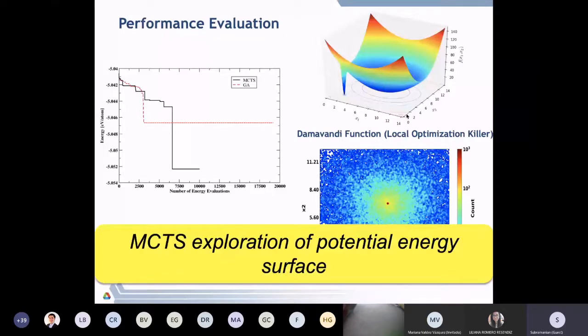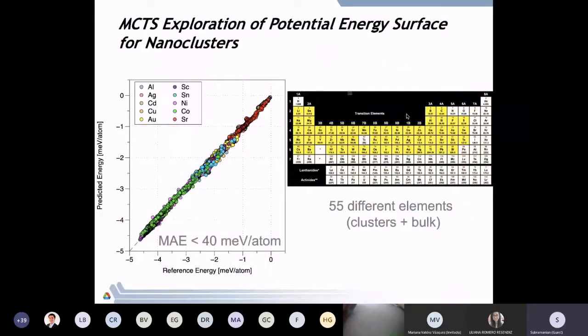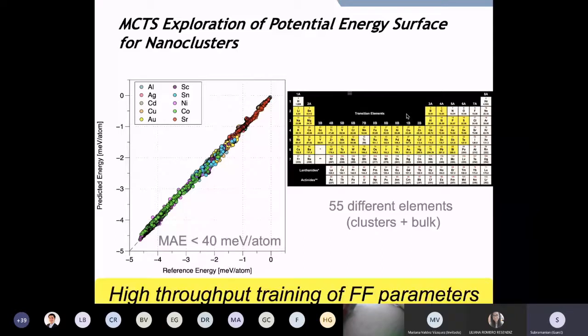So what we now did is that we went ahead and developed a force field for 55 different systems that had explicitly included training data for nanoclusters from DFT. And we came up with a model for 55 elemental systems. The process only takes a few hours to optimize the potential, and can be done on a single core, meaning that you can use your laptop to train force field parameters. So this is highly efficient and basically brings about this new era where we can do high throughput training of force field parameters. That is something that is a remarkable advance, we feel.